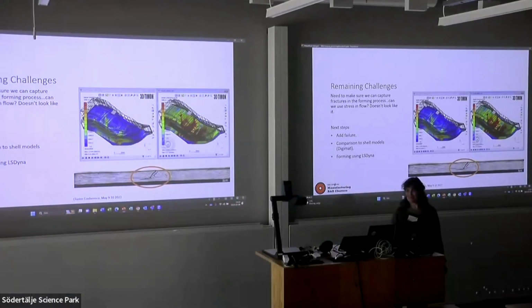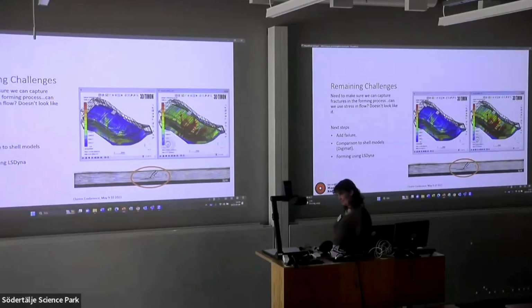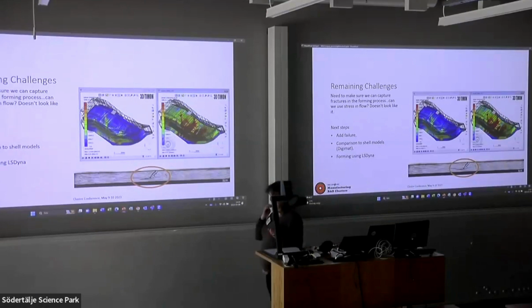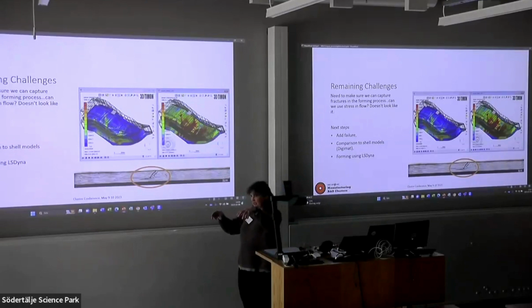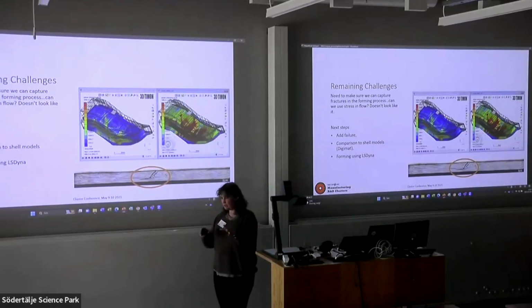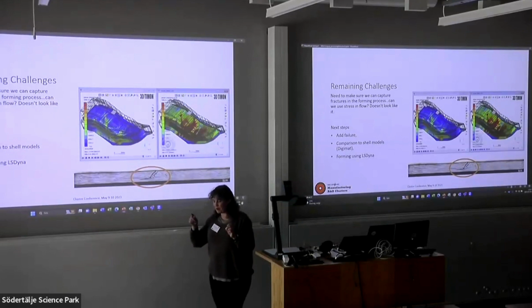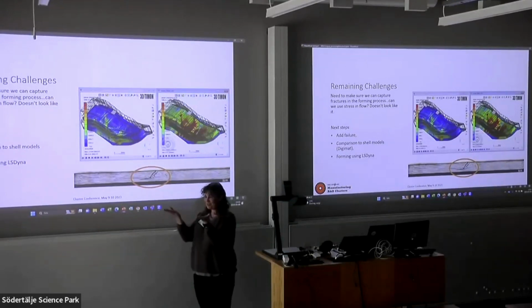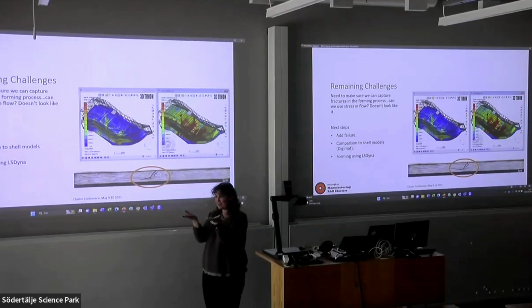Yvonne, you mentioned that the starting position is very important to get the modeling to work. How do you find the right start position? Do you experimentally test it out? You can put it in different positions, and then you can see what effect it will have in the flow, and you can see whether you can get a more even position. But one of the points with this is that if we're going to simulate it, we want the simulations to be in the same starting position.